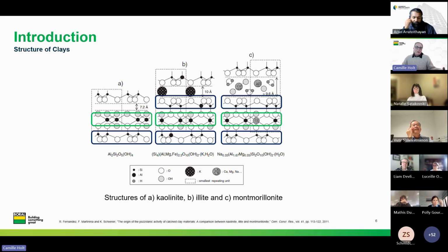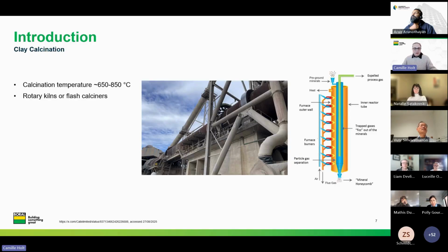So that's why we tend to focus on kaolinite - it generally produces a more reactive calcined clay. When you take a clay out of the ground, it's not reactive in its raw form, so we need to activate it. This is normally done thermally in a process called calcination. The calcination of clays at high temperature causes dehydroxylation, or loss of water, from the clay structure, and this disrupts the crystallinity of the clay and produces a more reactive material.